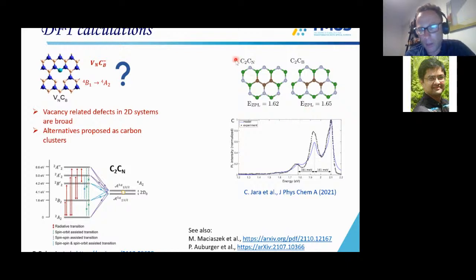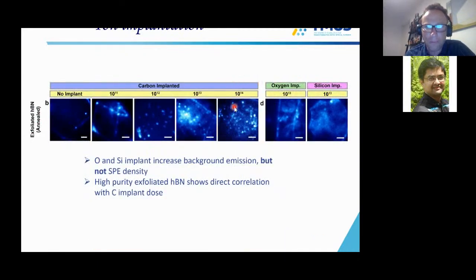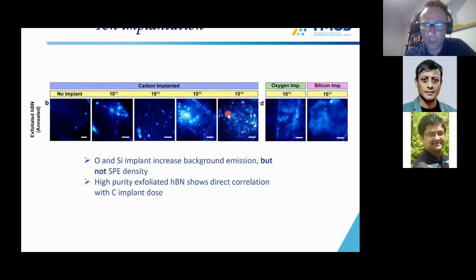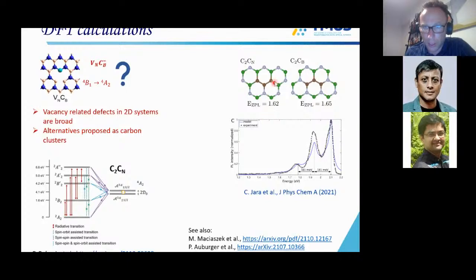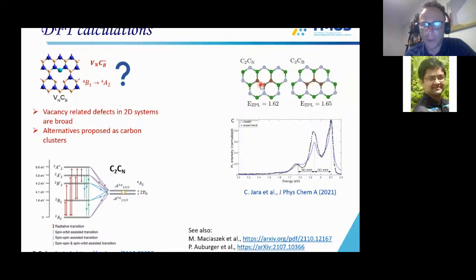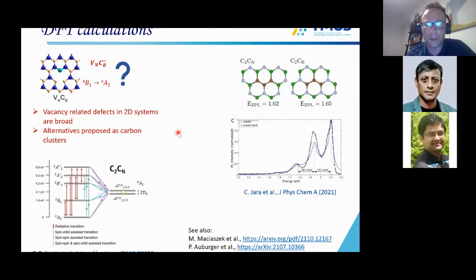And actually, this trimer is also a very strong supporter of our implantation results. Here I would like to spend a second to explain it, because if you are familiar with, for example, diamond or silicon carbide, you would probably know that it only takes about 10^11 to 10^12 nitrogens to get single emitters in diamond by implantation. But in our case, you really need to go to higher doses of about 10^14 to get a meaningful density. This tells you that the defect is actually quite complicated, and this carbon trimer supports it, because you really need 3 carbons to see only one defect. I mentioned there are other works as well that explain that there are some spin-dependent transitions, but I think the community is overall converging on these carbon trimers for these visible defects.